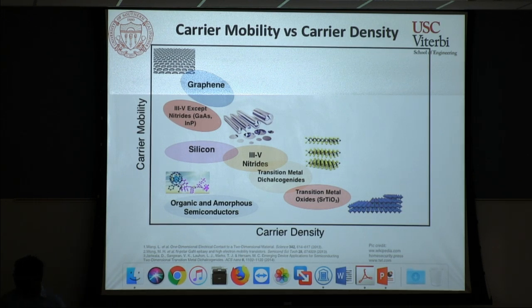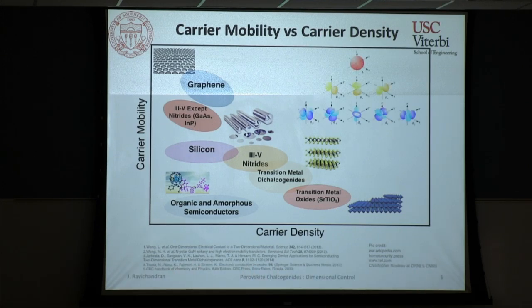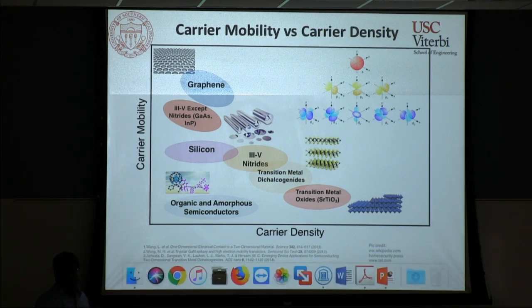To give a context to this, if you look at these materials, there are certain things that will jump out right away. Many of the materials that are shown within the high carrier mobility regime tend to have conduction and valence bands that have s and p orbital character. And having this orbital nature is the basic essence that decides why your carrier densities are low and the mobilities are high, because these bands are very, very dispersive in nature. But as you move down, as you get to transition metal-based systems, you move to the d-band conduction, where the carrier density goes up, but at the expense of the carrier mobility.